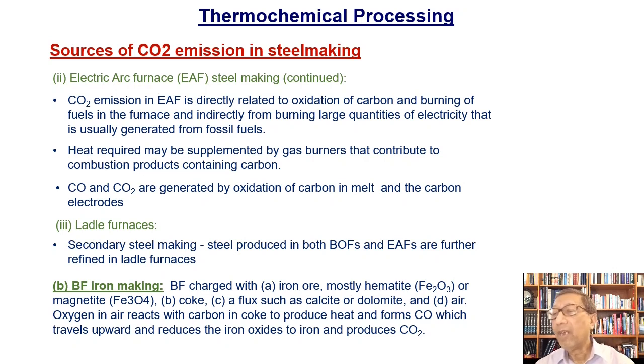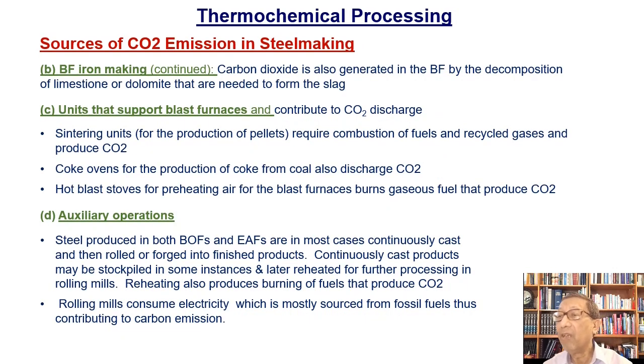And we shouldn't forget the contribution of the blast furnace iron making. So we charge iron ore, mostly hematite or magnetite, coke, which is primarily carbon without the volatile matter, a flux such as calcite or dolomite, which are carbonates, calcium carbonate or calcium magnesium carbonate. We supply air, and oxygen in air reacts with carbon in the coke to produce heat. And also it produces carbon monoxide, which travels upwards, reduces the iron oxide, and produces carbon dioxide. So that is another source of greenhouse gas.